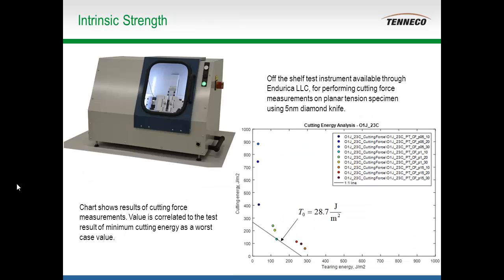So another test that's required is the intrinsic strength. The intrinsic strength test is basically a measurement of the minimum energy required to drive a crack through a single polymer chain. So there is an instrument available through Endurica, and there's also testing available through Endurica and Axel. I'd like to thank Axel for supplying this data that I'm showing here. This is one test that we have not implemented internally at Tenneco yet.